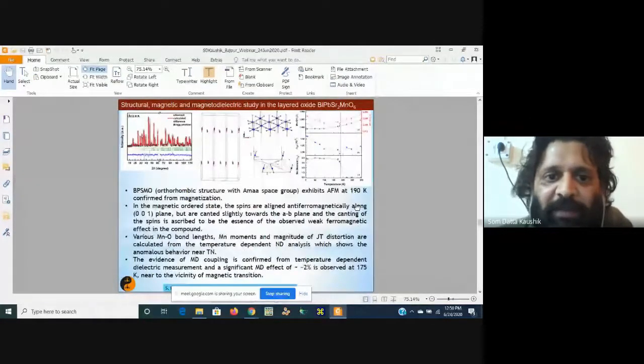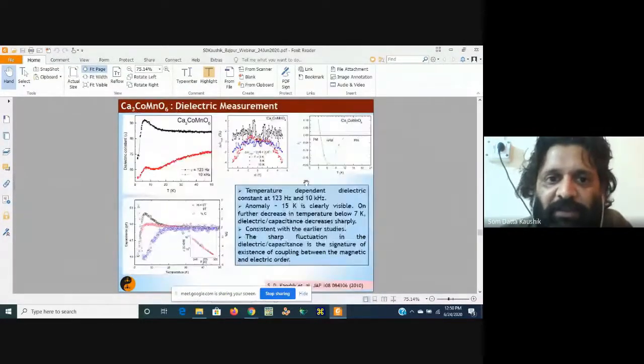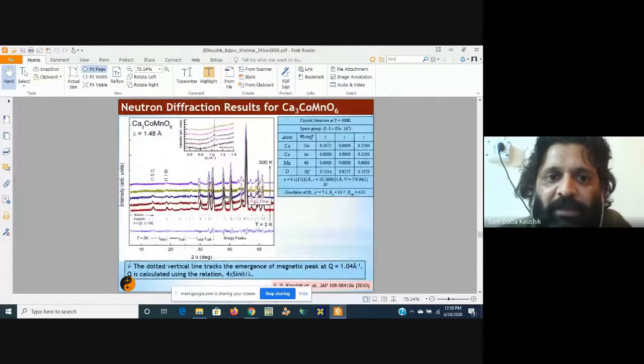And I'll quickly take one more example, for magnetic field effect, that I can show you. So this is calcium-3 cobalt manganese oxide. We have carried out neutron diffraction. This is another multiferroic sample. At 1.48 angstrom wavelength, we have carried out a diffraction. It shows antiferromagnetic behavior. So the spin structure looks like this.